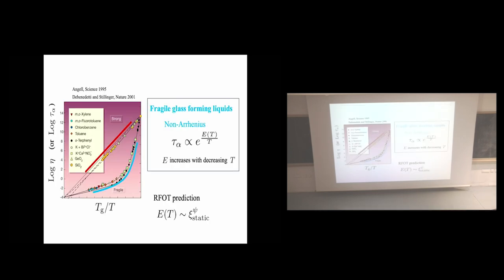Nevertheless, we can get some good understanding about, for example, the fragility of glass forming liquids. So as Camille mentioned, one of the remarkable features of glass forming liquids is that the viscosity or relaxation time shows non-Arrhenius behavior, this kind of banana curve. So this means that the effective energy increases with decreasing temperature.